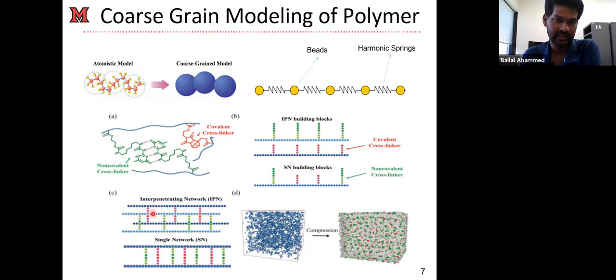On the other hand, other polymer chains will be connected by the non-covalent crosslinker. So this one. So there will be two networks actually, one wholly connected by the covalent crosslinkers, another network wholly connected by the non-covalent crosslinkers, and they are penetrating into each other. And we are calling it the interpenetrating network. This is actually very important because based on these network architectures, their mechanical and thermal properties differ, which is studied in this presentation.